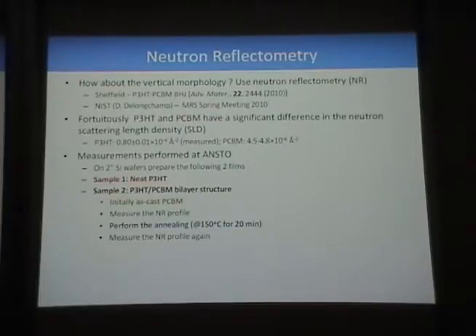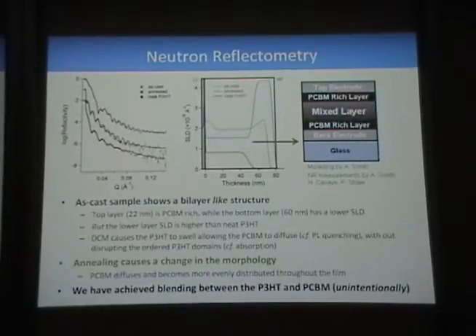So initially, this was the as-cast structure. We measured the neutron reflectometry profile, and after that, put it on the hot plate, annealed it, as we do for the device fabrication, and then measured the profile again. The top graph shows the obtained profile. So basically what you're looking at is the intensity of the reflected neutrons as a function of the incident angle. And you see these peaks because of the constructive and destructive interference of the reflected neutrons. So the red is the P3HT film, green is annealed, and blue is as-cast.